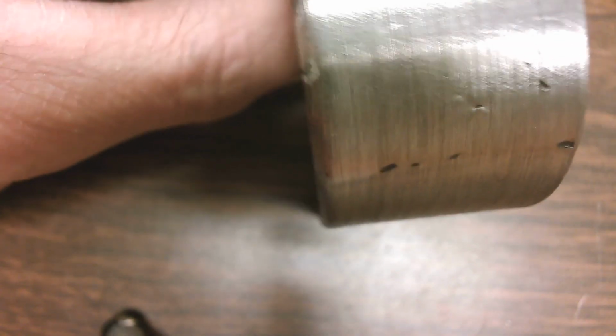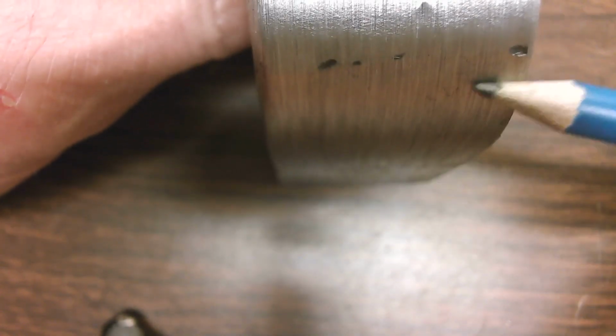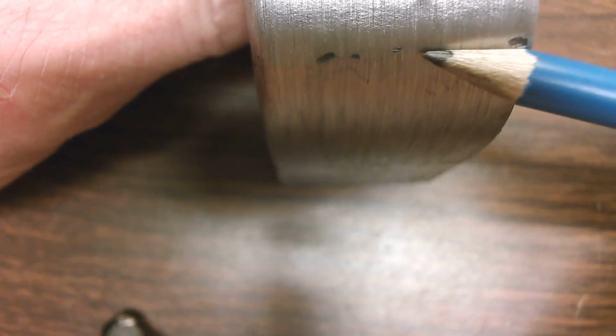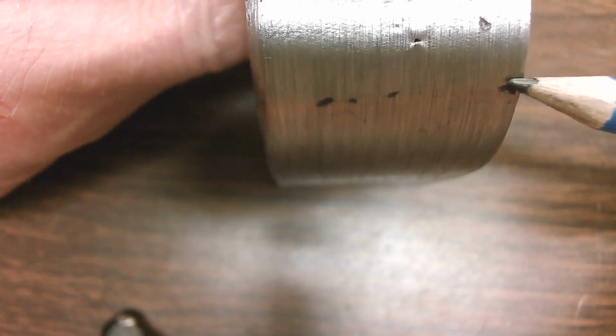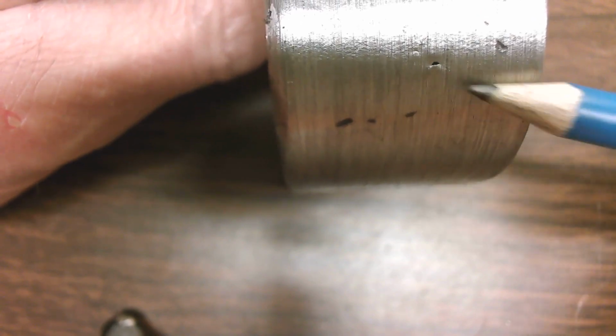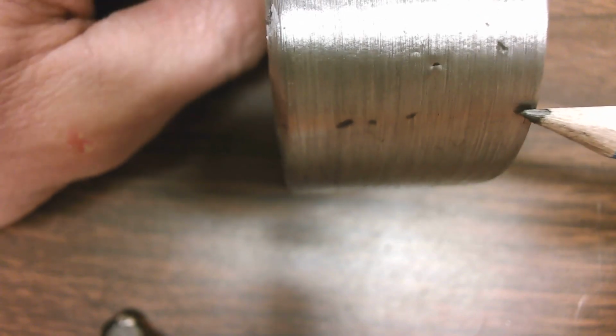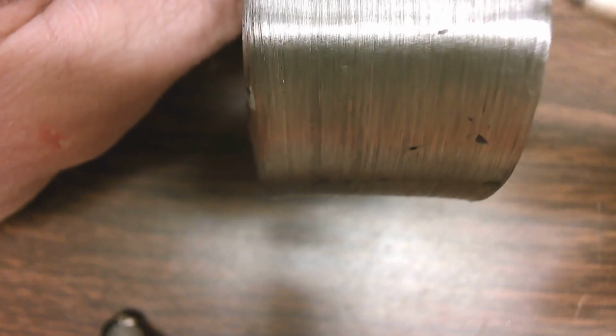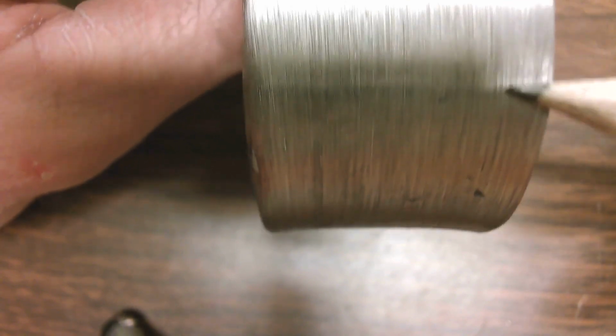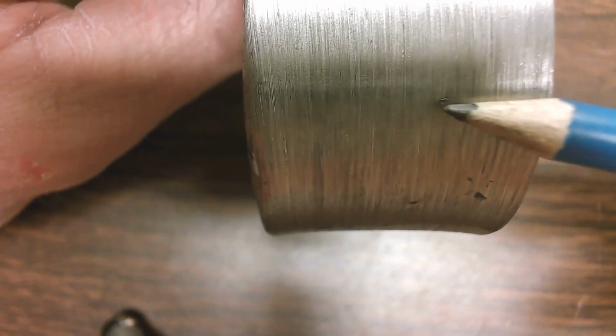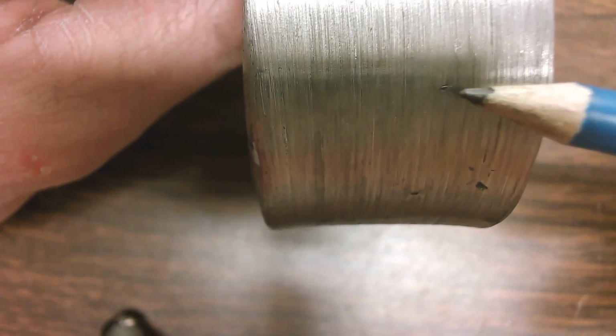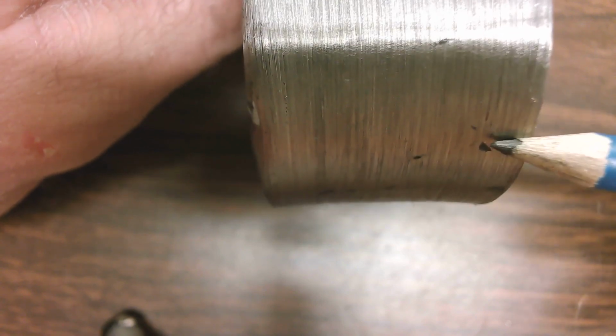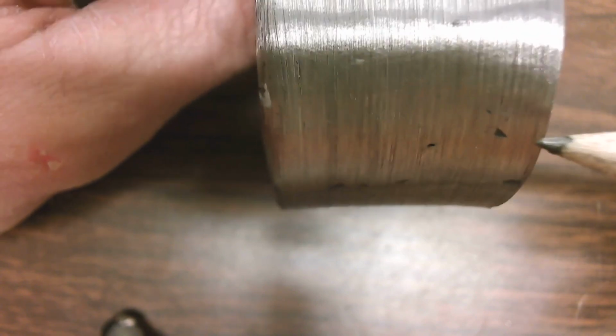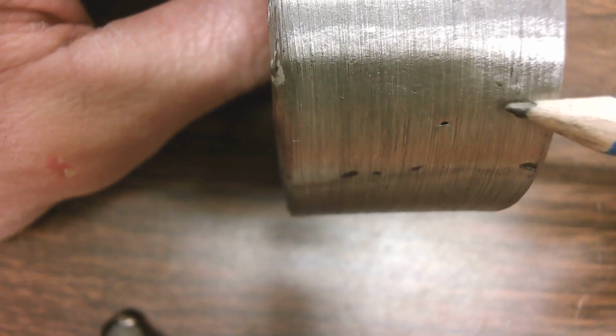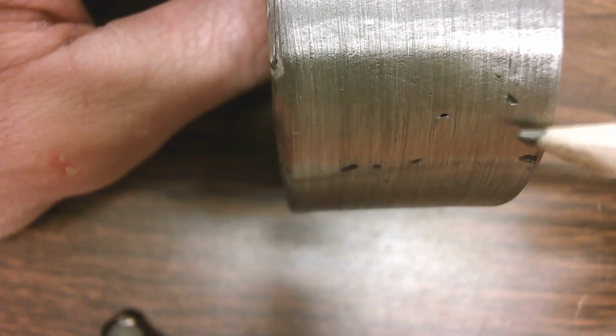We can see that. There's a heat signature kind of down here. There's a little bit of undercut that never got ground out, which is fine. Again, we talked about that. You don't have to grind the undercut. The coupon should be left 3/8 of an inch. And you can see right in here, there's kind of that shadow line showing the other end of the weld. We have a little tiny bit of maybe undercut there that never got ground out, and another one right there that's kind of inner bead between passes. There might have been a little undercut at the top of one that never got filled in.